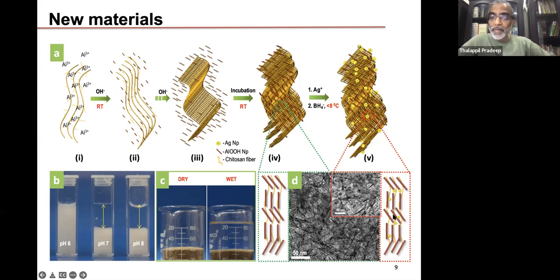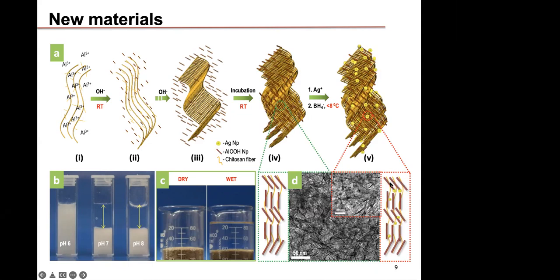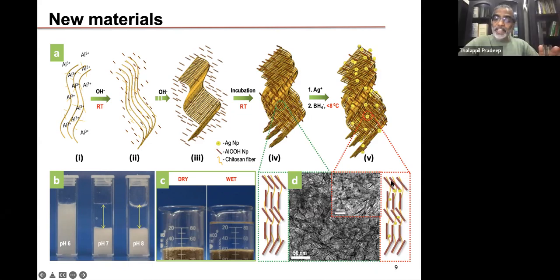What you see is a schematic representation of aluminum oxyhydroxide using a template of a polymer. You create a two-dimensional structure here. Really speaking, they are three-dimensional, and the three-dimensional structures look like boxes. So this particular thing is a sheet of about 50 nanometers long, 15 nanometers wide, and 15 nanometers in depth. Such kind of a box you can create. And in these boxes, you can put nanoparticles.